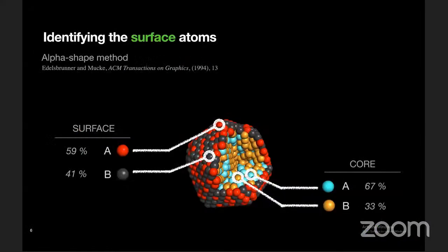So to make a quantitative analysis, and because we were interested in the surface segregation level or core-shell preference, we used the alpha-shape method to identify the surface atoms. Using this method, we were able to count the number of each type of atoms on the surface. That is, how many A atoms are on the surface, and likewise, how many B atoms are on the surface, and also for the core.